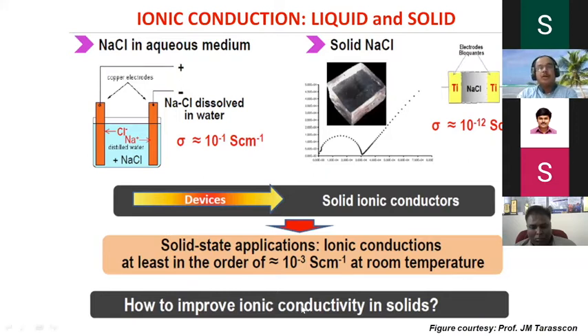Then sodium chloride: ionic conduction in liquid and solid, just for comparison. That's a very common salt. Sodium chloride dissolved in water has a conductivity of something around 10 power minus 1 Siemens per centimeter. The same sodium chloride as a solid crystal has a conductivity of 10 power minus 12 Siemens per centimeter. Just imagine why people prefer liquid electrolyte solutions. The conductivity is so good. The solid is almost 11 orders of magnitude lower than the conductivity of this.